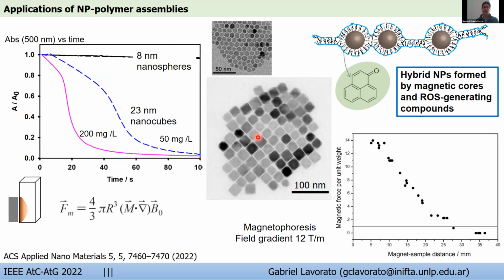So the problem was that 8 nanometer nanoparticles stabilized by the polymer cannot be separated magnetically with conventional neodymium magnets, because the magnetic force depends on the volume of the particles and is too low to separate them in a reasonable time, at least for the low gradients provided by these magnets. So we decided to use 23 nanometer nanocubes. As shown here, the larger size ensures an efficient separation in a few minutes, and this cubic shape also provides a large surface to load the hydrophobic molecules in the gap between the polymer and the capping.